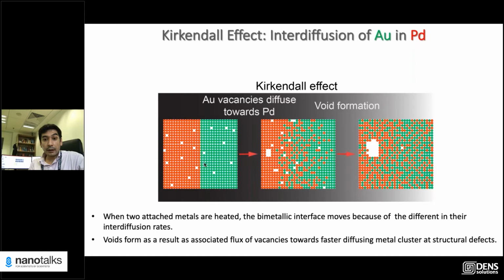It's because of the vacancies. As the particles are mixing, vacancies are going to flow towards the faster diffusing metal, right? Because all your metal is moving away, diffusing into the slower metal, and the vacancies from the other metal are going to diffuse in. Usually they form very stable voids, and these voids are, I should say, most of the time pinned. They don't move, right? So you start forming these hollow void structures, and this is referred to as the classical Kirkendall effect.